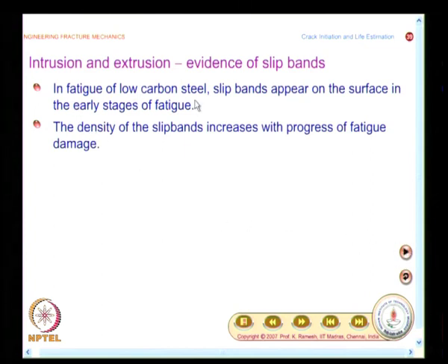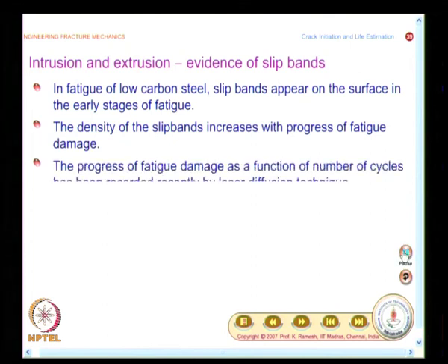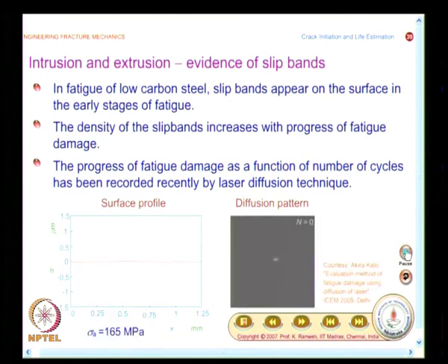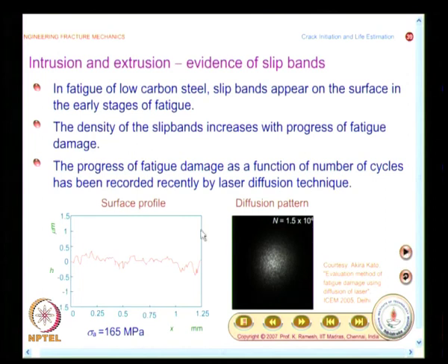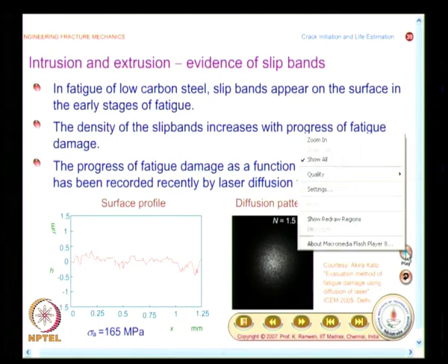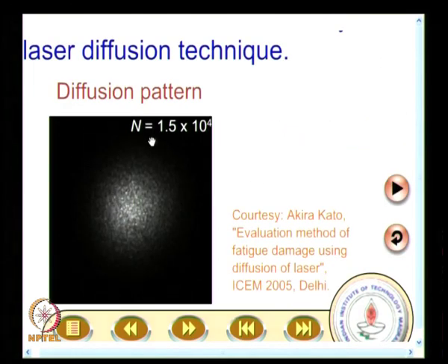In fatigue of low carbon steel, slip bands appear on the surface in the early stages of fatigue. And what does the theory say? The density of the slip bands increases with progress of fatigue damage. We would see that as part of the experimental result. The progress of fatigue damage as a function of number of cycles has been recorded recently by laser diffusion technique. And I will magnify this picture. Before I magnify, what I want to show you here is the surface profile, which was originally smooth, has become roughened here.